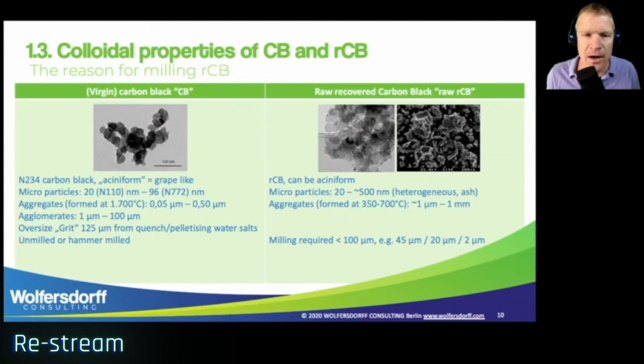Now let's look at how different carbon blacks and recovered carbon blacks look. The important information about carbon black is there are microparticles in the size between 20 nanometers and about 100 nanometers: 20 in the case of N100 grade carbon black and 100 in the case of 700 range ASTM carbon blacks. Now, you see the microparticles. These nano-sized microparticles are never alone.